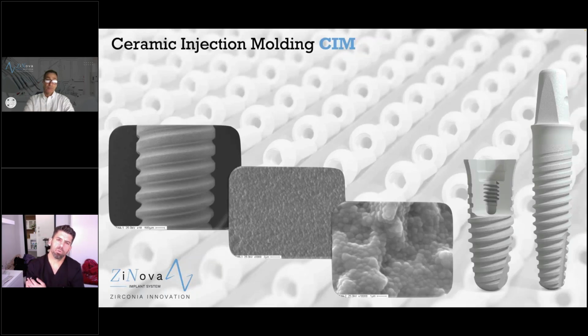And again, ceramic injection molding allows us to manufacture complex shapes. So in this case, we don't need any additional manufacturing process to obtain the rough surface, for example. So the mold has the macro, micro, and nano characteristics of the dental implant, where the porosity or the nano surface is within the mold. And then once the implant comes out of the mold, it is all ready to go. You don't need any additional chemical or sandblasting treatments to obtain that rough surface. It is already in the mold and it comes ready to use.